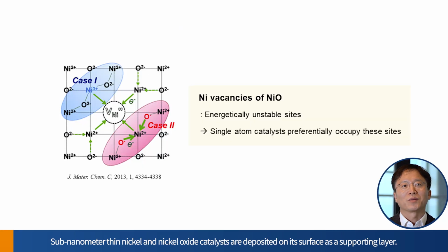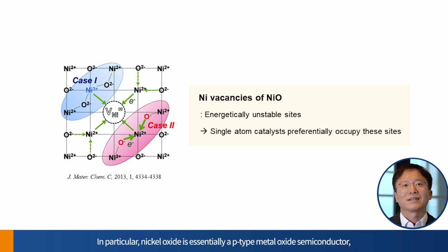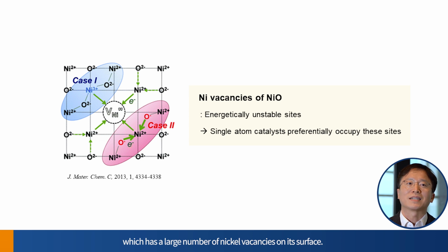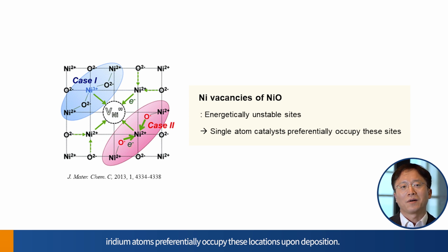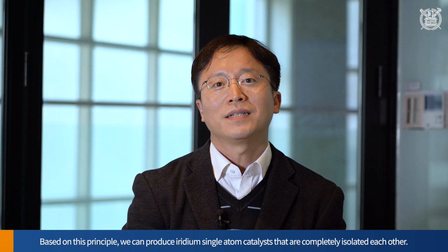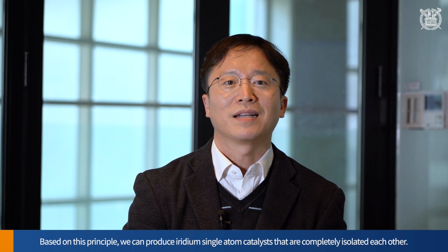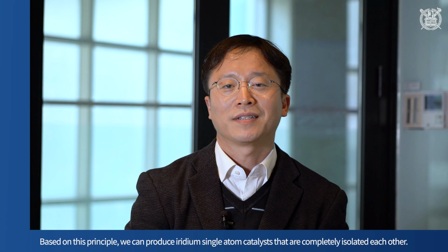In the photoelectrode developed by our team, the photo-absorbing layer is an N-type silicon semiconductor. Sub-nanometer thin nickel and nickel oxide catalysts are deposited on its surface as a supporting layer. In particular, nickel oxide is essentially a P-type semiconductor which has a large number of nickel vacancies on its surface. Since these nickel vacancies are energetically unstable sites, iridium atoms preferentially occupy these locations upon deposition. Based on this principle, we can produce iridium single atom catalysts that are completely isolated from each other.